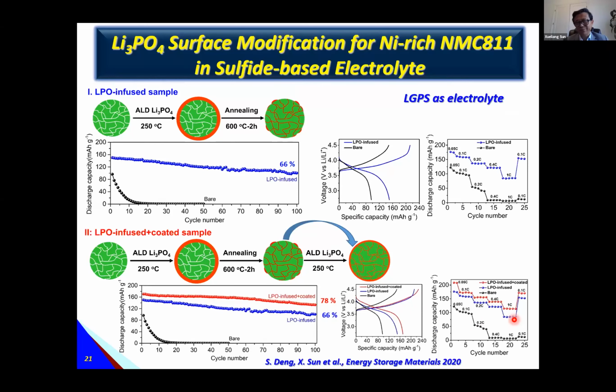So from this example, we see that solid-state batteries using sulfide-based electrolyte do have a very big challenge. Even using this kind of procedure, we still cannot get 92% capacity maintained, even at 200 cycles. And this one is just 100 cycles. So that means we need to develop a new approach to address the interface in this kind of system.